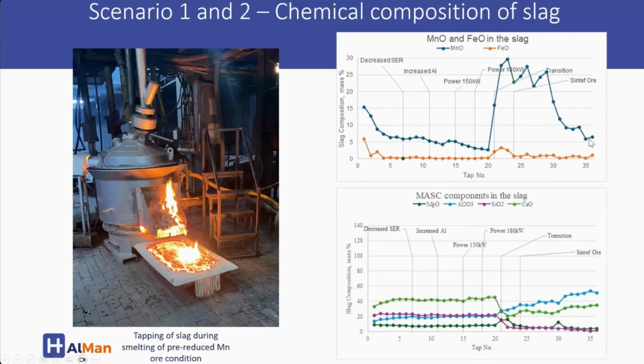What about the other major slag forming components? They were relatively consistent throughout the test work. You can see MgO there, it's quite consistent throughout, as well as lime, it's quite consistent throughout. But when you start smelting the pre-reduced ore, you'll see there was a jump here, because the more aluminium reductant we add, we had to also increase the lime so that we can flux the alumina that goes into the slag. That's why we see this jump here.